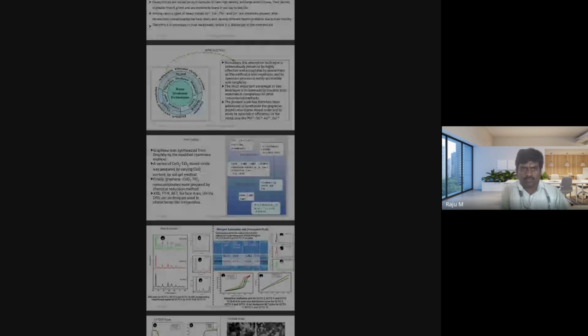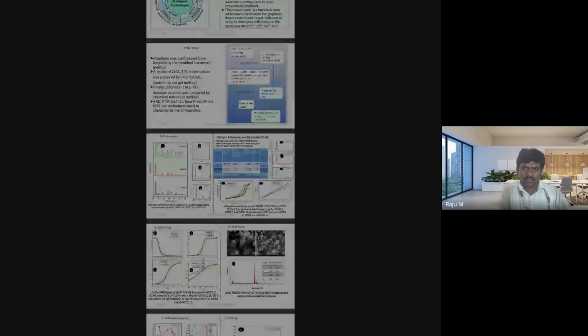Now come to the synthesis part. The graphene was synthesized by thermal method, and the series of ceria titania mixed oxides was prepared by varying the ceria content, and the graphene and ceria titania composites were prepared by a chemical method. And these samples are tested by XRD, FTIR, BET surface area, UV-visible DRS, and other techniques like AFM, TEM, etc.